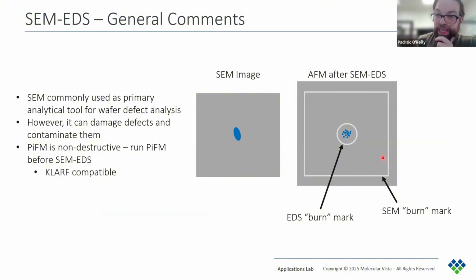So for SEM and EDS, most of our examples are from defect review wafers, so I can't show that data, but I want to make some sort of general comments on this. SEM EDS is used as the primary tool for wafer defect analysis. And while it's very powerful, on the chemical side, it will only give elemental information, which is not ideal for ultra-thin residues or organic contaminants. But also SEM and EDS can contaminate the sample, which can be seen here in my relatively crudely drawn image.